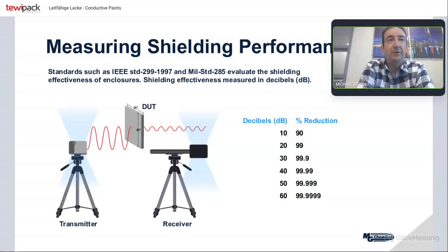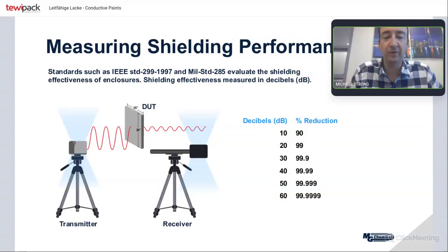With most applications for RFI EMI shielding, a lot of customers along any frequency range want a minimum of 40 decibels. That's just common. Some people would want less, but we see more and more that customers want a minimum of 40 decibel shielding. Some of our coatings at higher frequencies can do up to about 100 decibels. That's pretty premium performance. But typically you're somewhere between 60 and 100 decibels attenuation per our latest testing of the IEEE standard.